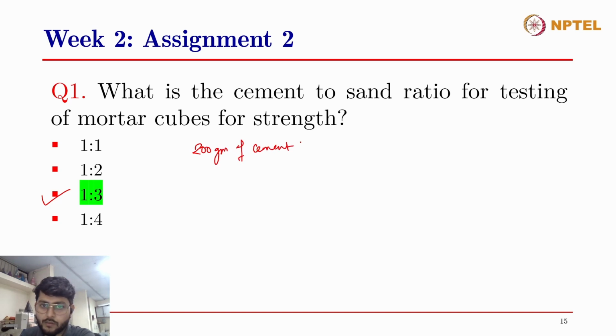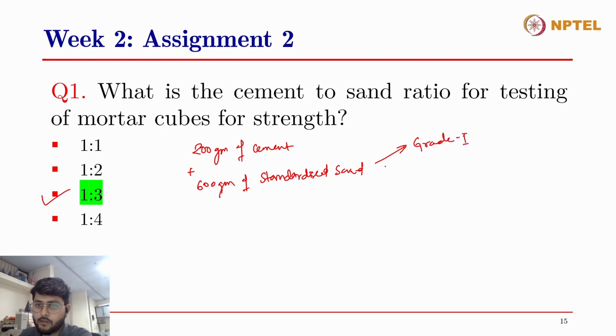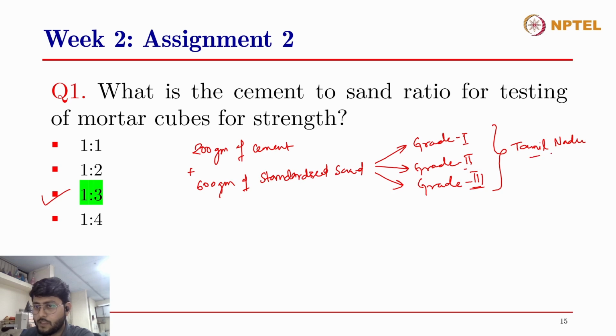Basically, to make each mortar cube, for a given cement, if you want to know the strength of the cement, you have to make mortar cubes. For each of these mortar cubes you have to take 200 grams of cement and 600 grams of standardized sand. The standardized sand has to be taken in equal amounts from 3 grades: grade 1, grade 2, grade 3, based on the sizes of the standard sand. The Indian standards mention that this standard sand has to belong to one of the regions of Tamil Nadu. I don't remember exactly, but it is somewhere around Ennore. It is called Ennore sand, I guess.